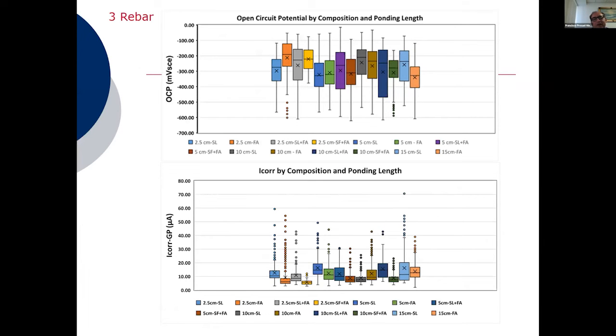So let me continue here and show you, we did this type of plot that tried to capture the first quartile and the average potential as a function of the reservoir size and composition. And you can see that the average for most of them is more negative than -300. So in general, most of them are active, but the values have spread over time. And here we are observing that in some cases, the more recent values might be more positive.